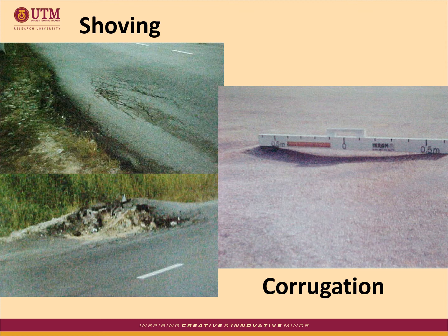Okay, here we have shoving and corrugation. Shoving can occur at locations having severe horizontal stresses, such as intersections. It is a formation of a wave on the road surface where we have braking or acceleration movement of the traffic. It is caused by excess bitumen, too much fine aggregate, or a weak granular base. And then corrugation is a formation of plastic movement or wavy surface where the distortion is perpendicular to the traffic direction.